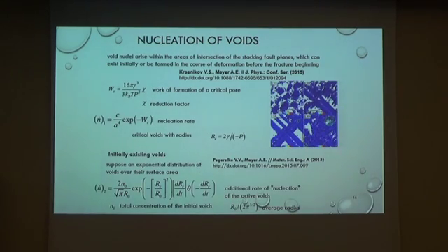And also we consider some kinetic model of microfracture. It's a nucleation of new pores, and we think that there are two regimes of this nucleation. It's a nucleation of really new pores and an activation of existing pores.